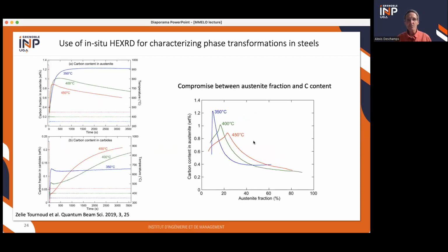So when you make a carbon balance, if you say I have basically no carbon in ferrite and my carbon is evolving in austenite, I know the austenite fraction. So I know everything about the carbon. Some part is in austenite, and it goes up to about 1.2% at 350, a bit lower at higher temperature. It goes through a maximum, which means I have carbon enrichment and then carbon depletion. And if I have this carbon depletion, this is because of carbide formation. And you can get by a difference the carbon content in carbides.